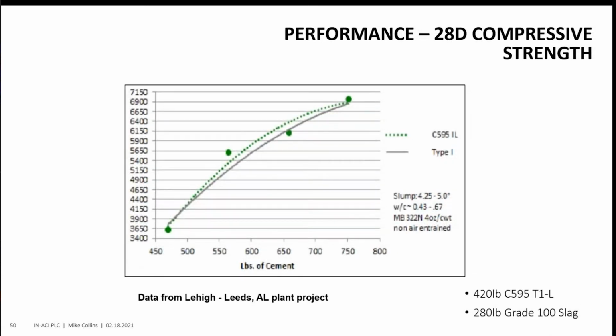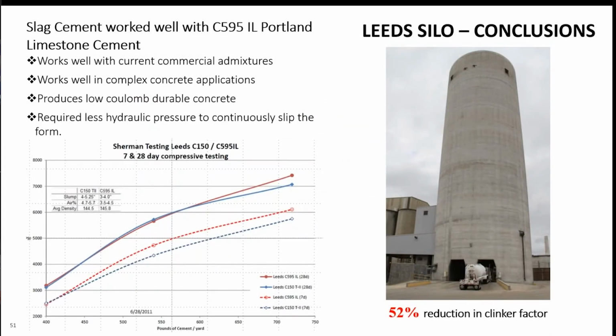And the 28-day compressive strength pretty much saw that same trend hold true with the PLC breaks above the type 1 breaks. And so some conclusions that were made after this project was over was that you saw the slag cement work very well with the type 1L Portland Limestone Cement. Current admixtures that were available for that project worked extremely well and predictably. It works well in complex concrete applications, produced a very low Coulomb durable concrete, and actually required less hydraulic pressure to continuously slip that silo.